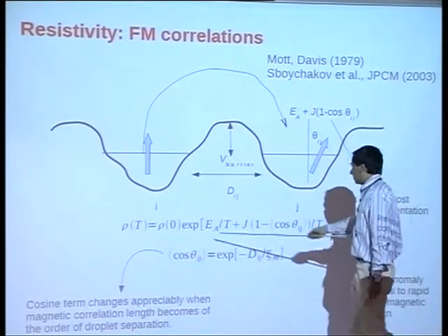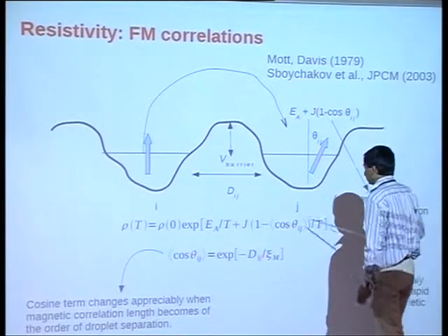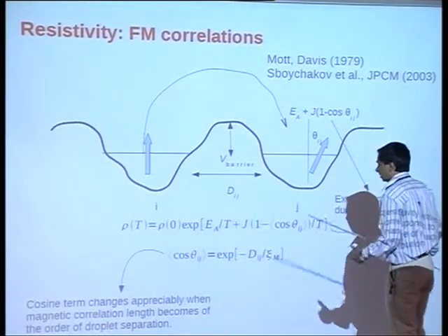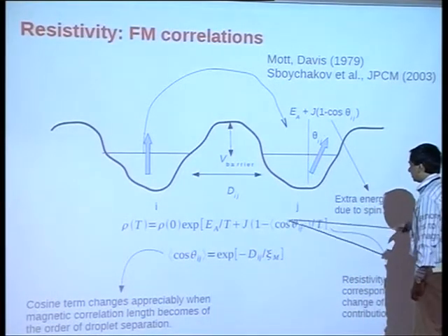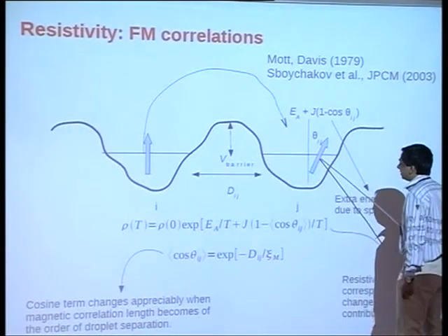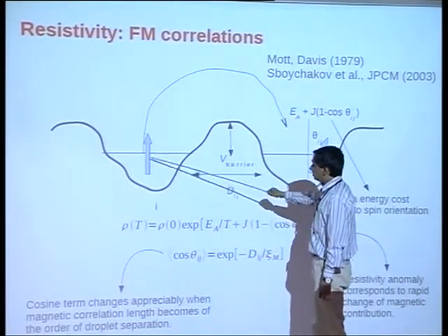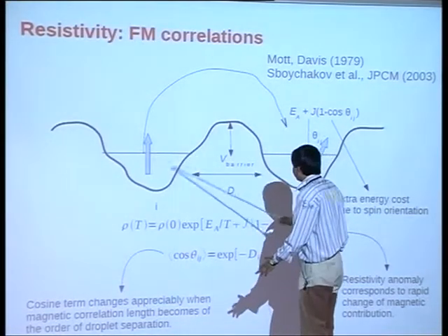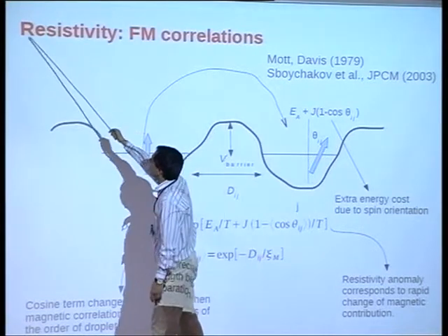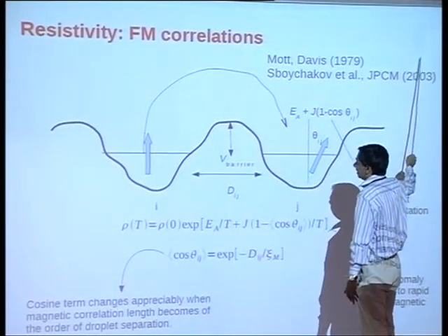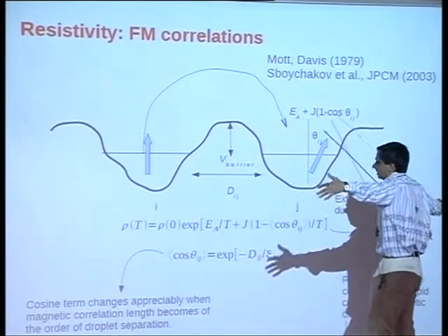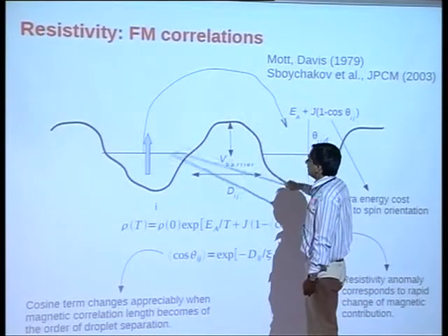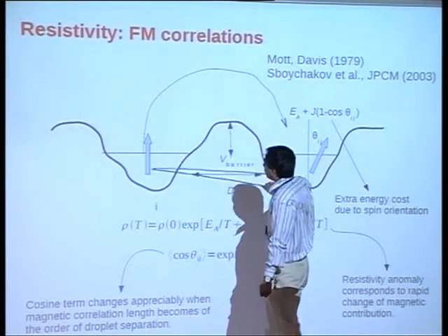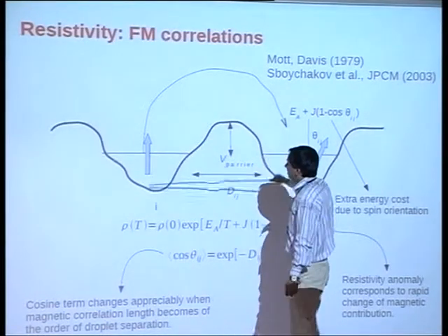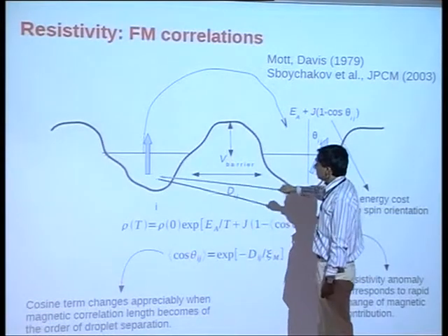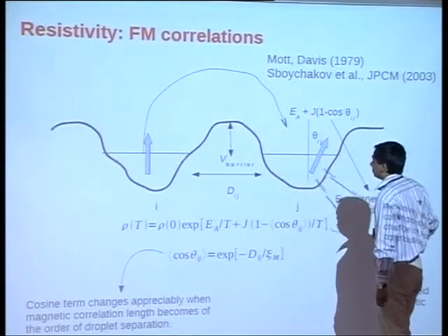obtain a very simple expression for resistivity. One can do other things also, not just this one. We just do this for modeling. And this term is basically the correlation between spin polarizations in different puddles. Note that these are not dictated by dynamics in this layer. Basically, there is a big cloud of Mn hovering over, and in general, it will have magnetic correlations which are typically at low temperatures on a much longer length scale. Nevertheless, it will have fluctuations of magnetization, and therefore, puddles lying directly under corresponding manganese polarizations will show alignment like this because of wave function overlap.